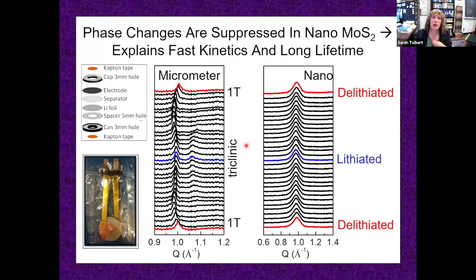So we're charging and discharging here. And we see that a new peak appears in the bulk. In the nanometer scale system, there's no peak. And this is one of our batteries that has an X-ray window put in it so that we can actually take X-ray diffraction on our battery while we cycle it.